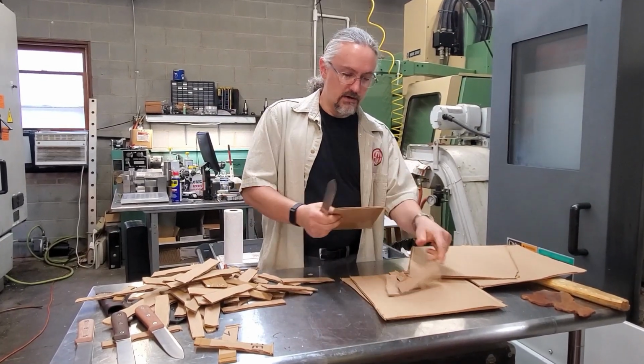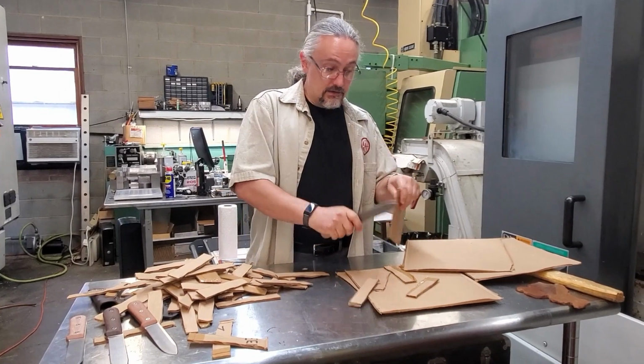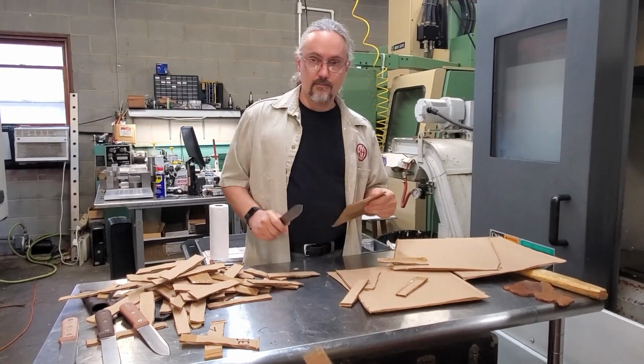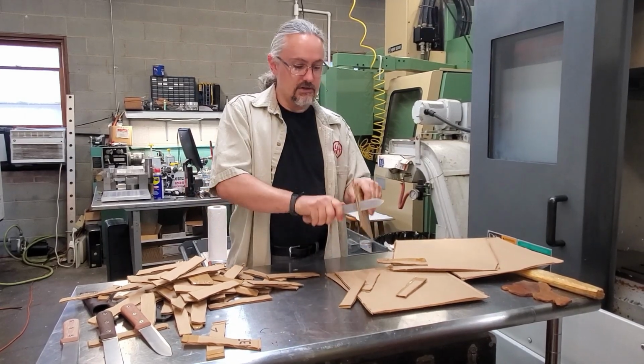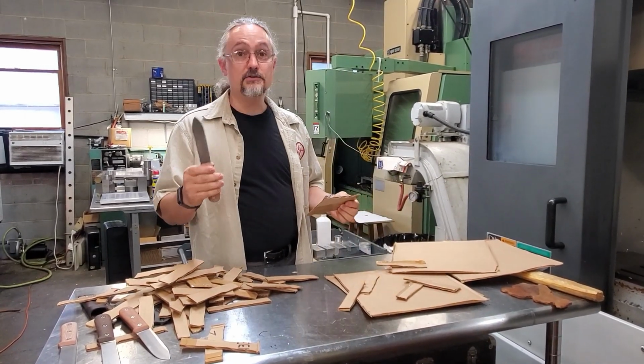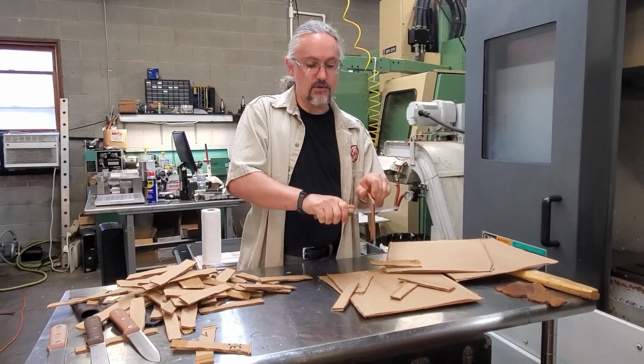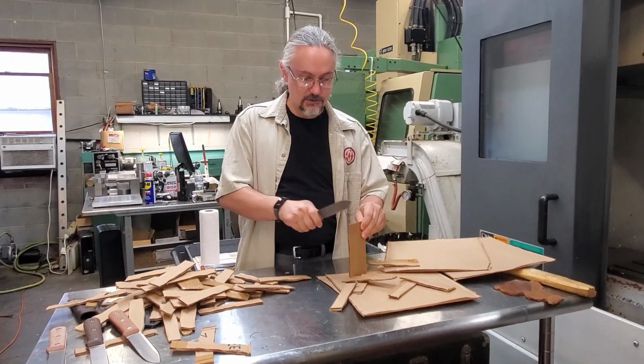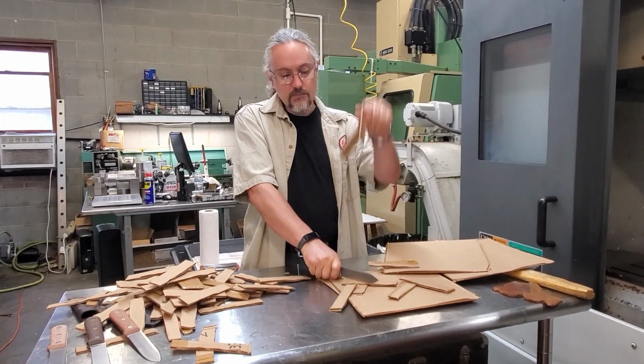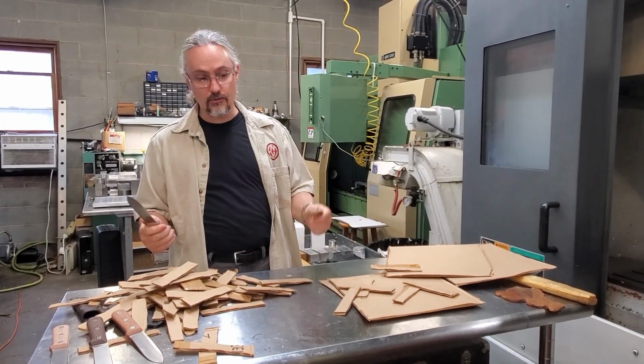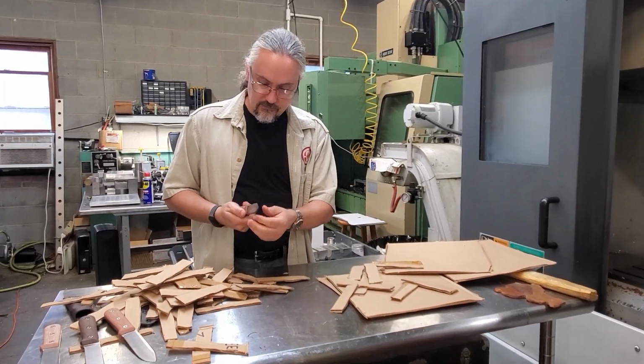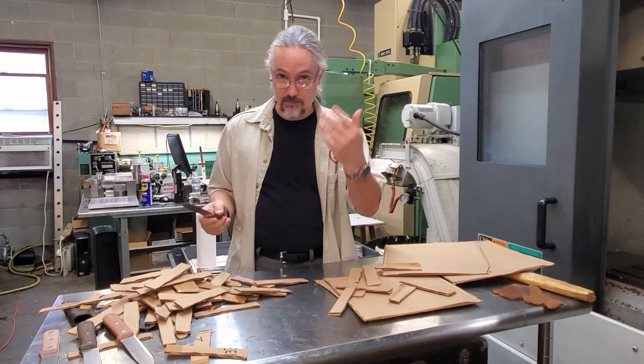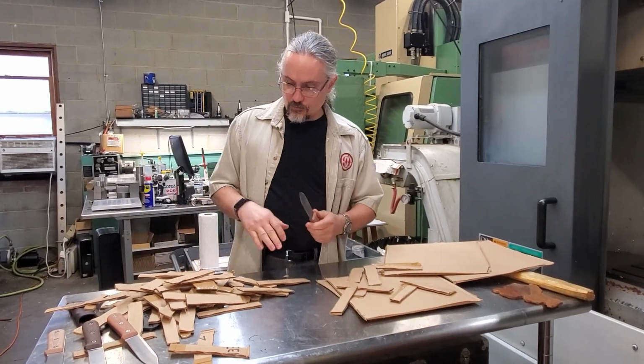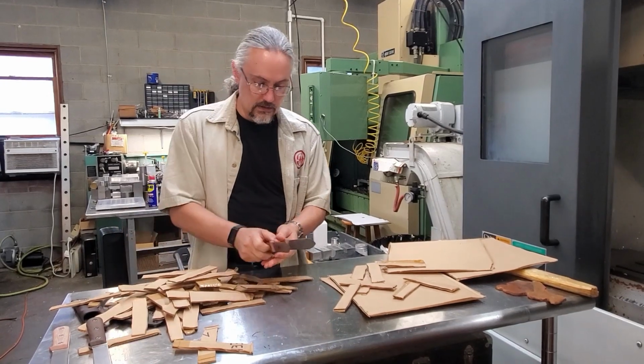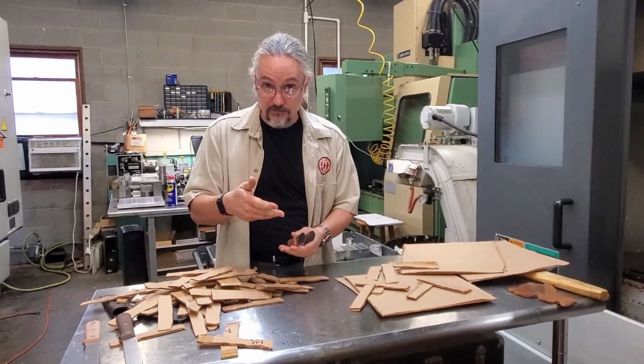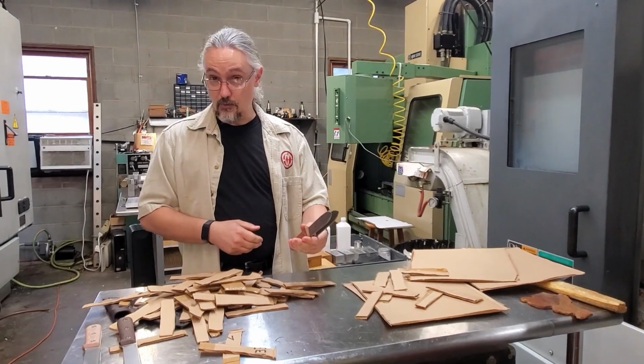I wish there was a quantitative number, but to my knowledge, there is not any measurement that you can make that gives you a hard number that will tell you whether or not you're getting the edge stability that you want. And this is the reason we use the low temp temper in the first place, is edge stability. So knives go dull cutting soft abrasive stuff like cardboard, and you can see that very easily. And so what I'll do when I'm doing this, and I'm not shooting a video, is I'll cut all this cardboard, same amount of the same cardboard, and I'll look at them next to each other under bright light and under magnification, and I can kind of start to see which ones are going dull and which ones aren't.